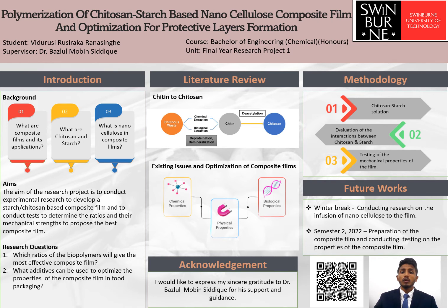Hydrophilic compounds such as polyols, most commonly glycerol and sorbitol, are used in starch and chitosan films to improve their mechanical and barrier properties. The recrystallization of starch restrains it from coming into real practical use because it easily becomes rigid and brittle during long-term storage and therefore loses its value in use. Overcoming the brittleness of starch while achieving full biodegradability in blends can be accomplished with the addition of biodegradable plasticizers such as glycerol. The methodology of my research project consists of three major parts.